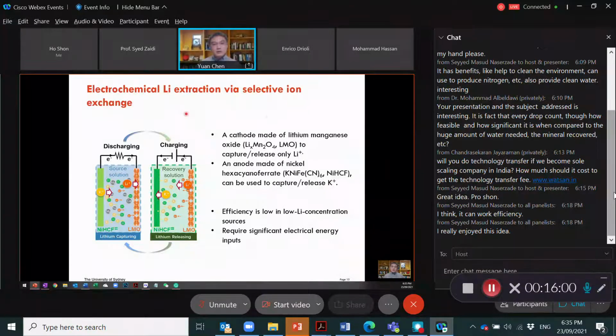Now, we are focusing on this particular type of configuration, which is the selective ion exchange. I think some of the students may be working on this area, so you may be familiar. What we are doing here is we have two electrodes. One is based on lithium manganese oxide, which is basically an intercalation type of electrode material. The lithium will be able to go in. And on the other side, we use a Prussian blue analogue, the nickel hexacyanoferrate, nickel HCF, which can capture and release the potassium.